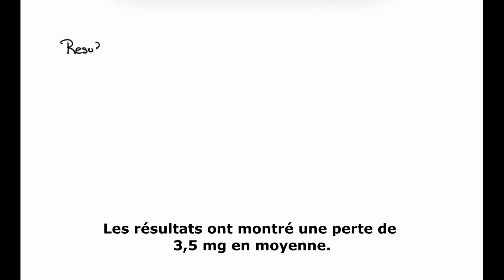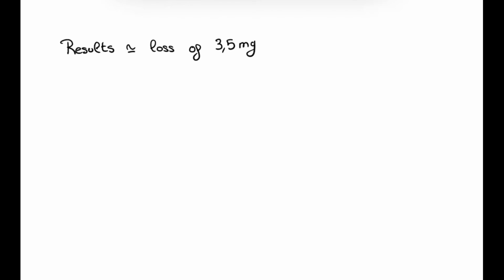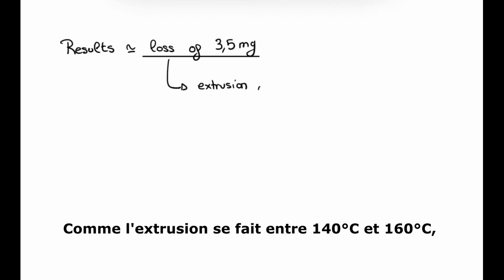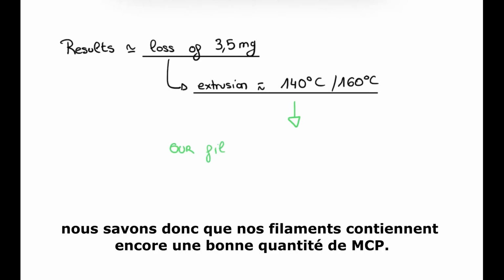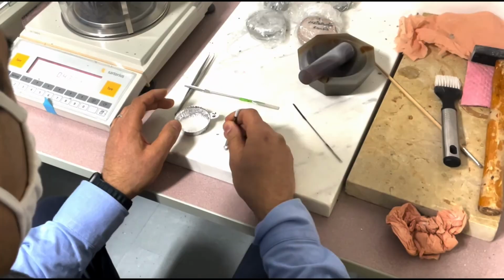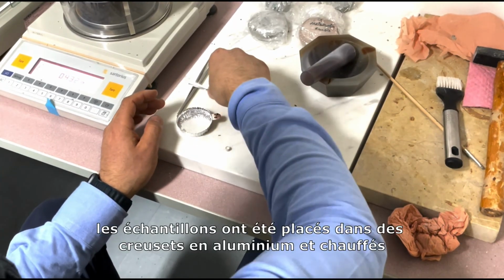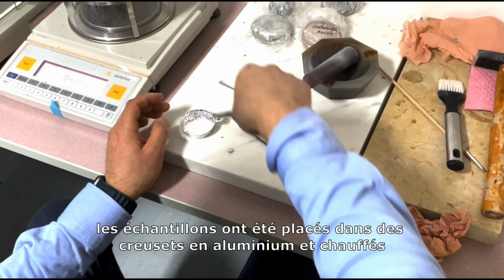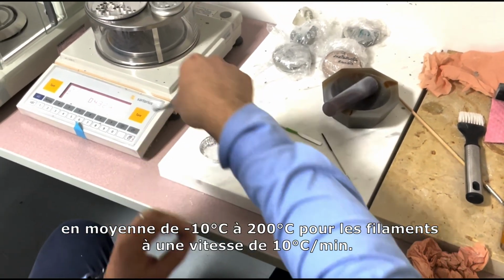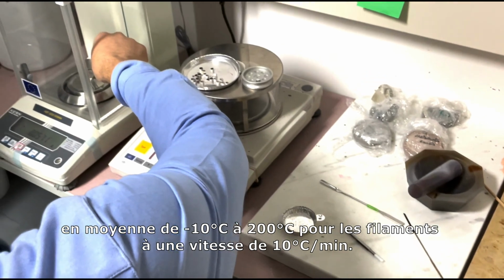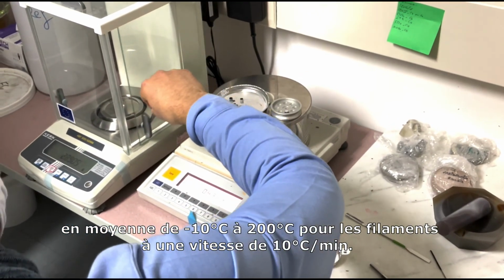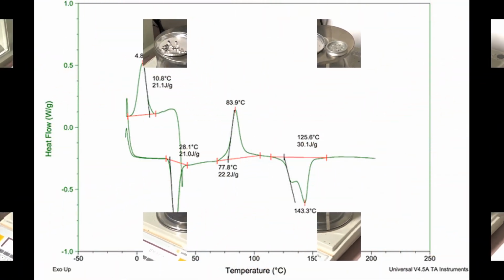The results show a loss of 3.5 mg on average. As the extrusions happen between 140 and 160 degrees, we thus know that our filaments still contain a fair amount of PCMs. For the DSC analysis, samples were placed in aluminum crucibles and heated on average from -10 degrees to 200 degrees for the filaments at a speed of 10 degrees per minute.